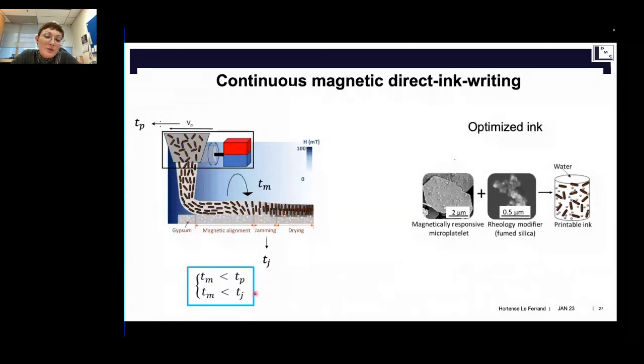So here we had to optimize one thing: the time to align the platelets should be shorter than the time for printing, because this guy is going to move forward, right? And the time for drying. So we need to make sure we have these kinds of relations. To do this, we developed an optimized ink that contains magnetically responsive microplatelets, the same as before, but we added fumed silica as a rheological modifier to make the printable ink.